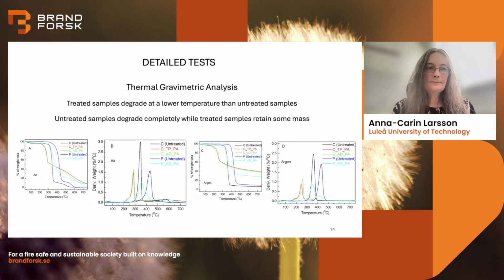Thermal gravimetric analysis can be done so we can see at which temperatures we lose mass. This is in air atmosphere. Here we first lose some mass from water evaporating. Here the flame retardants start to break down, and this breakdown, as we'll see later, causes charring that prevents further breakdown, so it's a very slow decrease in mass here. The untreated samples degrade almost completely, and then some small residue is slowly combusting until all mass is lost. This is the derivative of the curves.